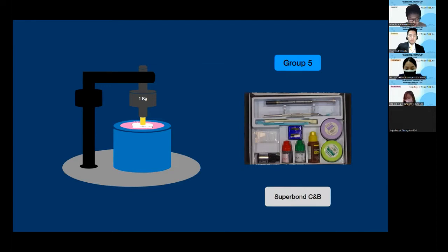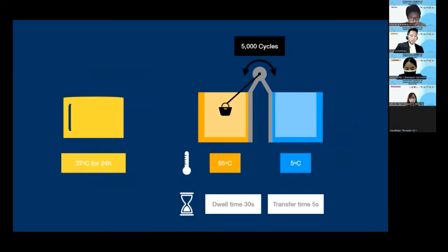The dentin surface was treated with green activator in the Super-Bond kit, and the components were mixed according to the instruction using the bulk mix technique. Then the cement was applied on the dentin, the composite cylinder was loaded, and left for complete polymerization for 8 minutes under the 1 kilogram of loading. Then all the samples were stored at 37 degrees Celsius in the incubator for 24 hours, then subjected to the thermocycling process for 5,000 cycles.